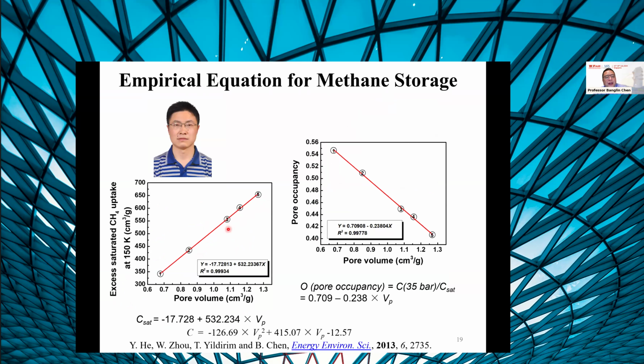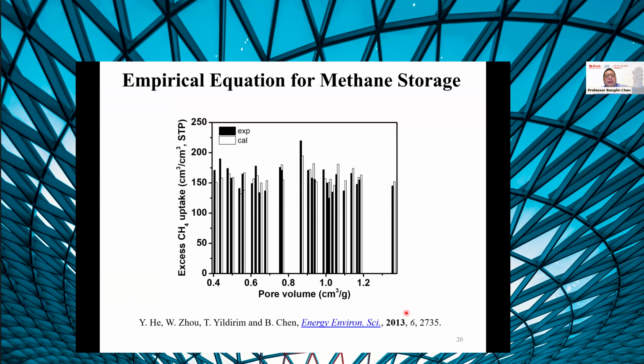And we also realize the empirical formula for this methane storage capacity means that we are able to calculate the methane storage capacity from the pore volume. And because nowadays, once we know the crystal structure, we can estimate pore surface and pore volume, then we can calculate methane storage capacity, so significantly reduce our time and facilitate screening to discover high performance methane storage material. And you will see the calculated and experimental ones match quite well.